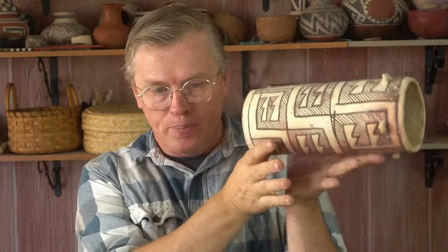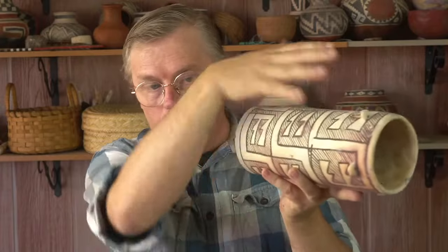Look at this. This is that same paint recipe again. So on this, it was sitting like this in a firing. It was propped up on rocks, but it wasn't getting good air down here, right? Because there were logs around it. And so the top oxidized really well. See? It oxidized nice. It's still reduced in places, but the bottom reduced like crazy. And that copper did that red thing, which it does if it reduces. So this is what happens if you reduce copper.